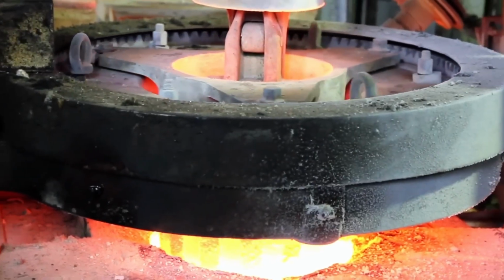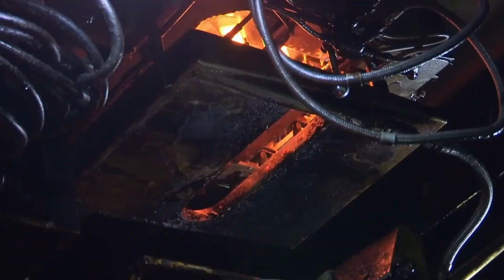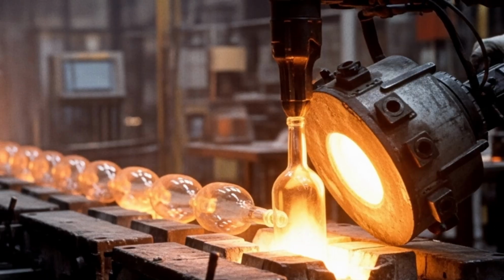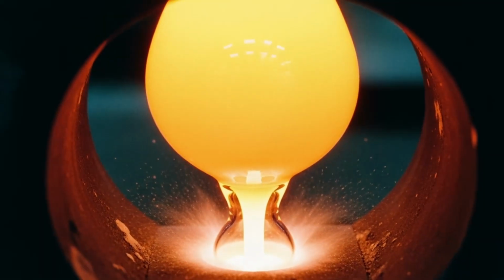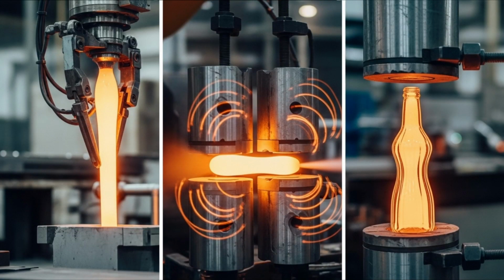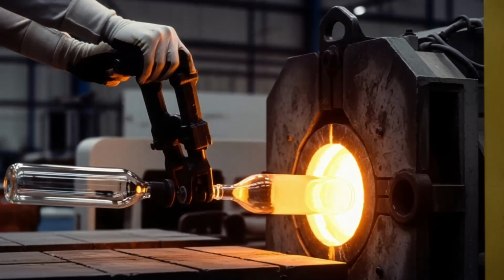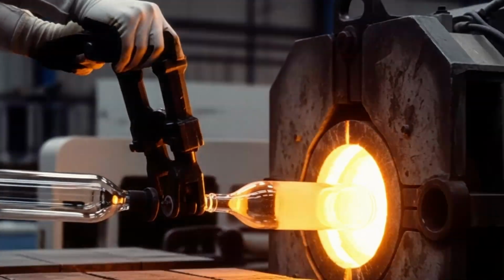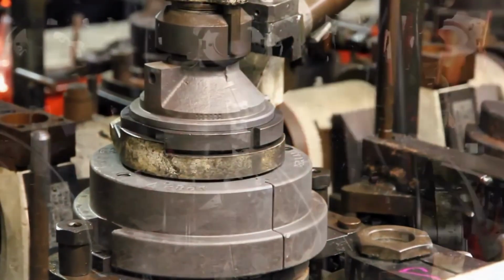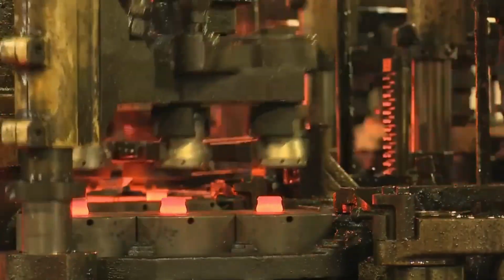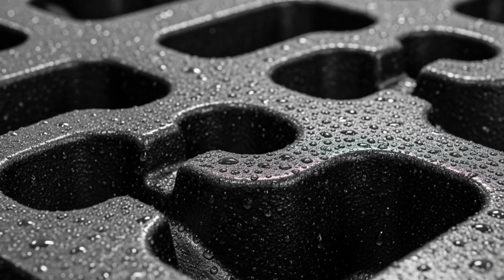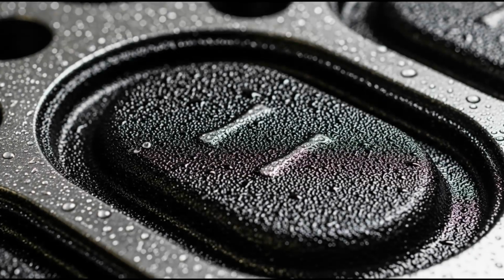The process is fascinating. Small portions of molten glass, called gobs, are cut at about 1,100 degrees Celsius. Each gob drops into a preliminary mould, where a jet of compressed air expands it into an initial form known as a parison, a hollow tube with a neck. That parison is then transferred to a final mould, where another burst of air inflates it against the mould walls, giving it its final shape in seconds.